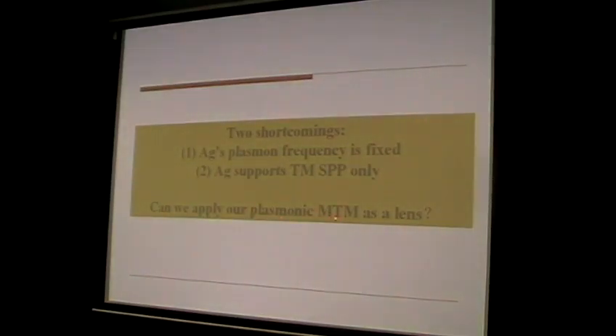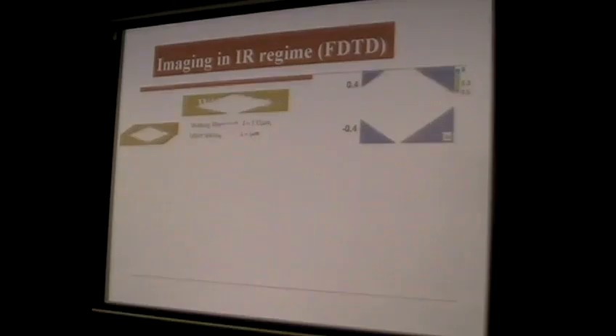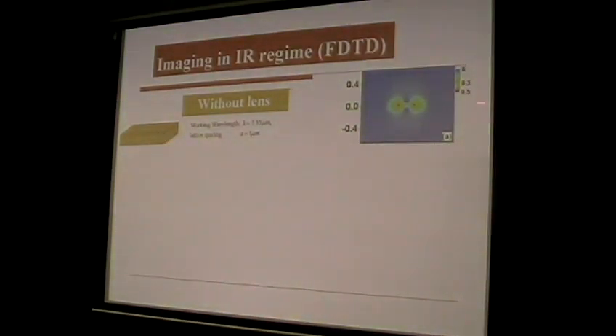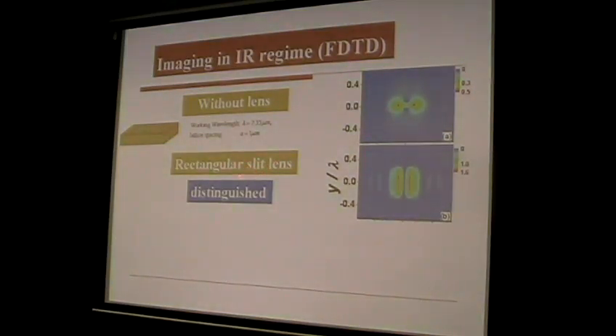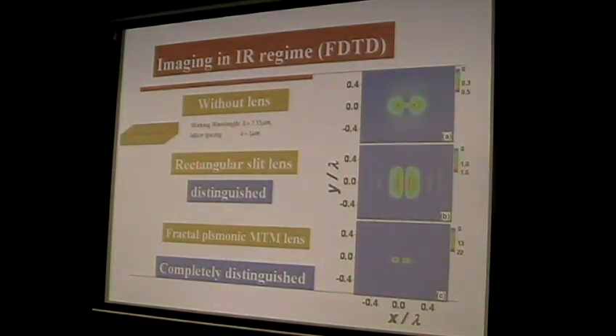Now the idea is, can we apply our plasmonic material as a lens? Indeed, we found that we can. We performed FDTD simulation to study the imaging in the infrared frequency region. Here are two sources placed at this position. Without a lens, we measure the field distribution along this direction, on this plane, and we found that the two sources cannot be distinguished. If you use the rectangular slit lens, which I mentioned before, you'll find that they can be distinguished along this direction only. For this direction, it does not exhibit the subwavelength features at all. If you replace the rectangular slit lens by our fractal plasmonic material lens, you find that the two sources are very clearly distinguished with very good resolution.